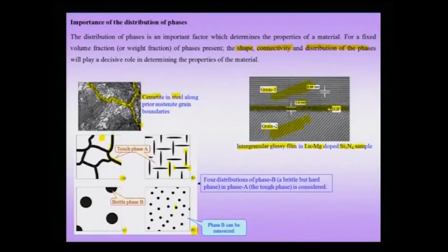But now I have 2 further distinguishable cases even for the spherical case, one the case D which has been shown here and one the case C. In case C and case D, the volume fraction of phase B is the same, which as I told you is a brittle phase, but the size of the precipitate in the case of C is larger. What does this mean in terms of the properties? What is meant by size here?